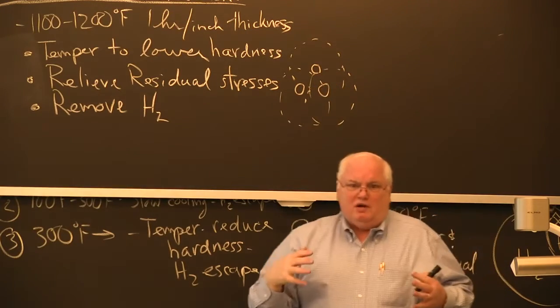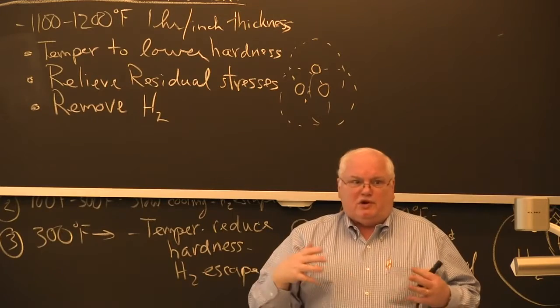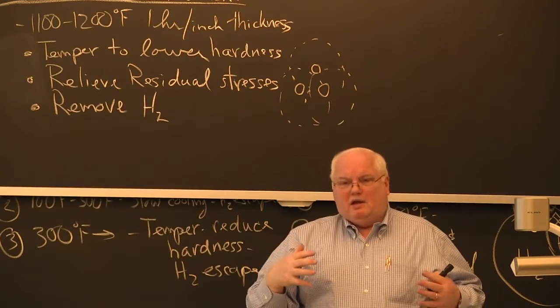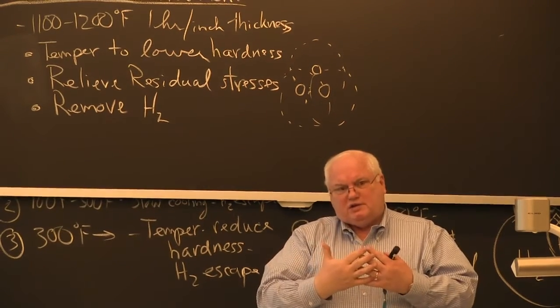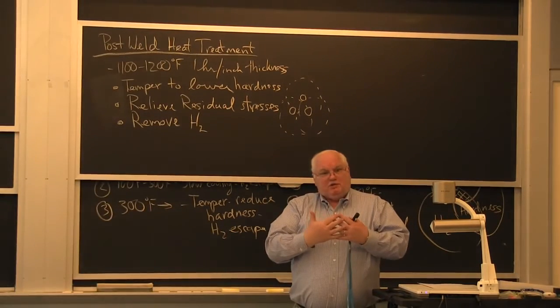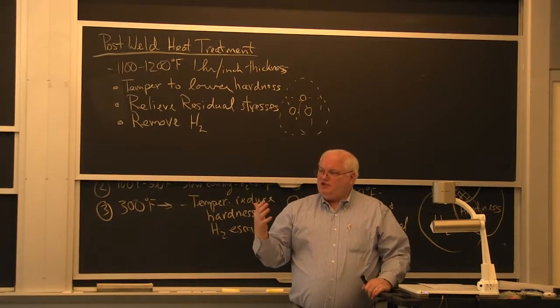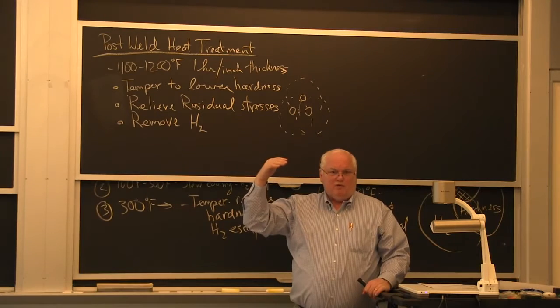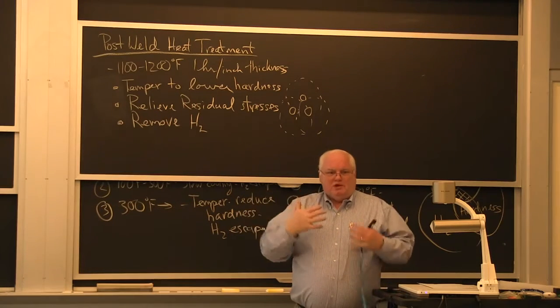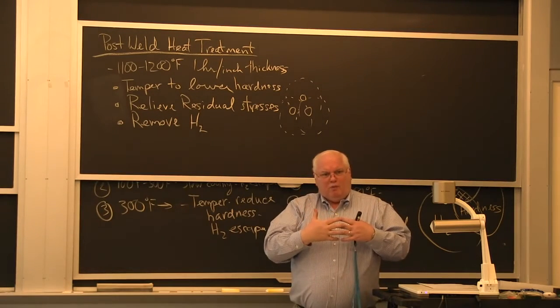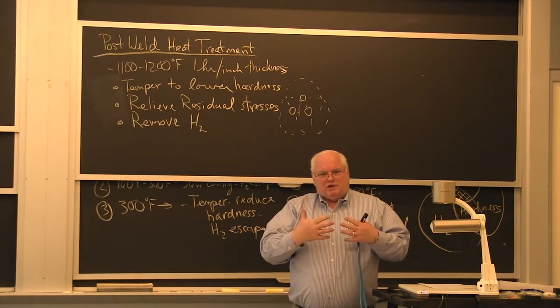The material at 1100 to 1200 degrees, this is called stress relief heat treatment. And the locked-in stresses, there's enough creep in the steel. The steel actually loses about half of its yield strength when you get to 1100, 1200 degrees. And that means the steel can actually start to deform and relieve those locked-in stresses.